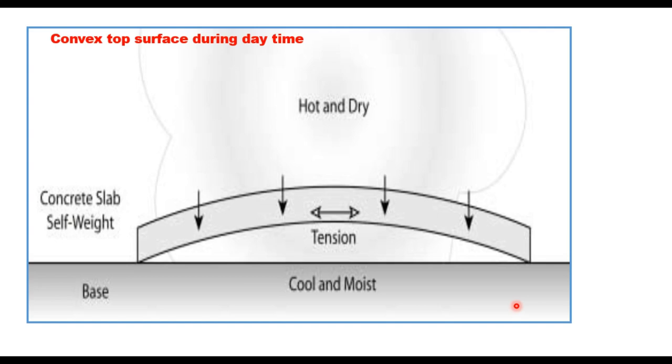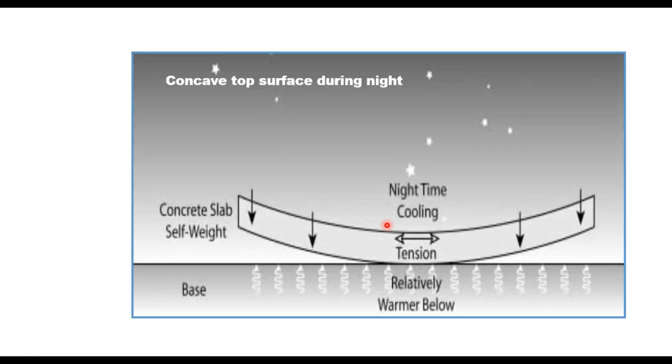During daytime, the surface is hotter than the bottom and the slab will curl up, forming a convex surface like this with the raised central region, and the test in the raised part will show high deflection values. The edges will be resting on the foundation in this case. Similarly, edges will get raised during the night and test at edge will give large deflections. And these factors should be considered while carrying out the test.